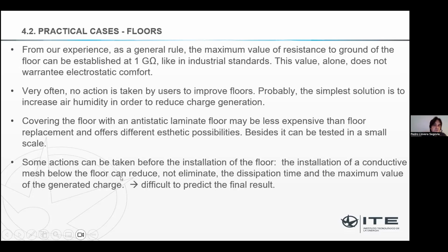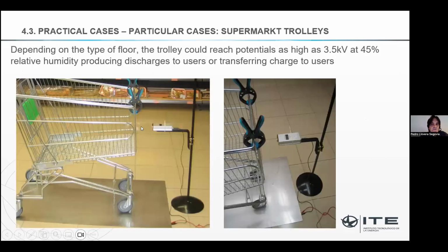Anti-static laminate floors, or some action can be taken before the installation of the floor. We worked in one case with a marble floor, and they put a conductive mesh below, but it was difficult to predict the final result. I think in the end it works, but it's a risky operation if you cannot make some tests before installing the floor. We also worked, I will skip this because I have no time, on a problem in supermarkets with trolleys.